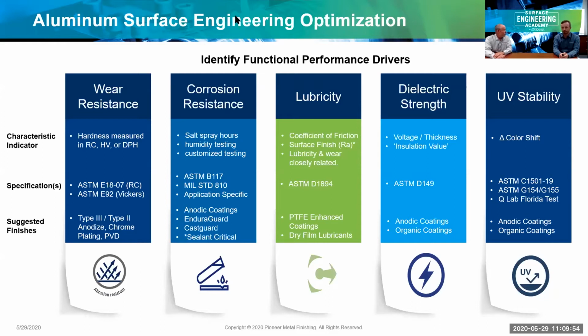Or corrosion resistance might be the primary attribute that you're looking for. There's organic coatings such as paint that do a very good job, but anodizing also does a great job for providing good corrosion protection to the aluminum. One of the main advantages of anodizing, though, over a paint type of a coating is it is converting the aluminum to aluminum oxide. It's becoming an integral part of the surface, and it's hard, so you can't scratch through it, and you don't have the issues with creep corrosion that you have. Corrosion, yep. Yeah, grown from the base layer.